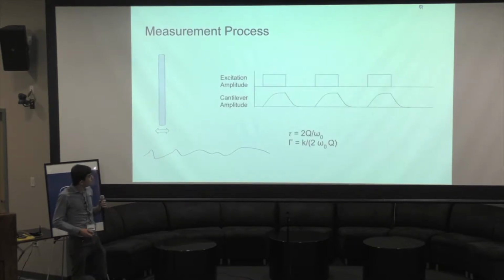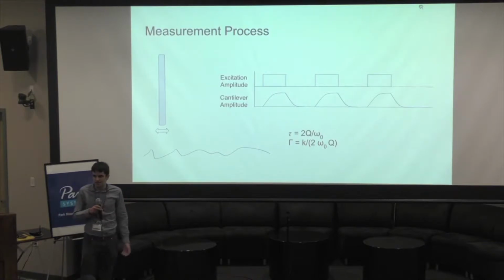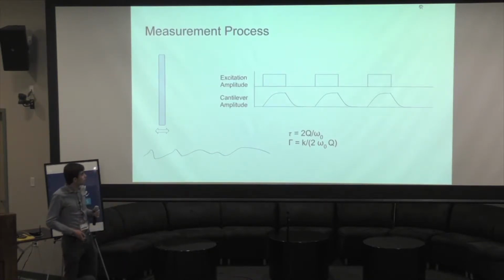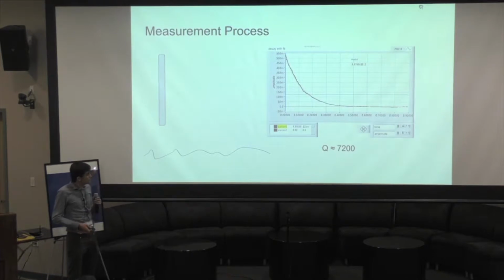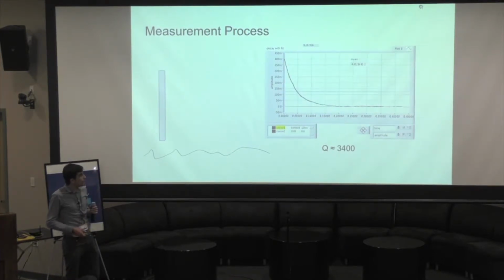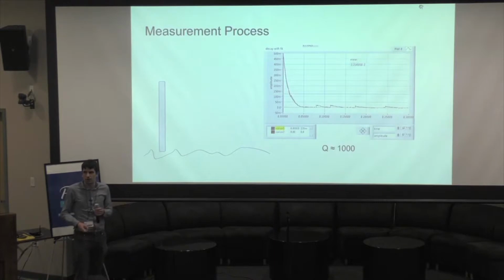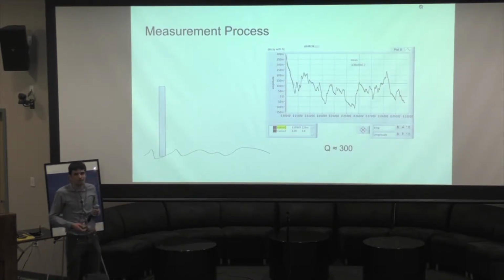And then we lift up, and to measure the dissipation or the quality factor of the cantilever, we excite it by applying a pulse with the shake piezo at the resonant frequency, and then allow the cantilever's motion to decay. The quality factor is proportional to the time constant of the exponential decay. Then we repeat that measurement at several heights approaching the sample, and we see the quality factor decline until we finally hit the sample, and we don't see oscillation.